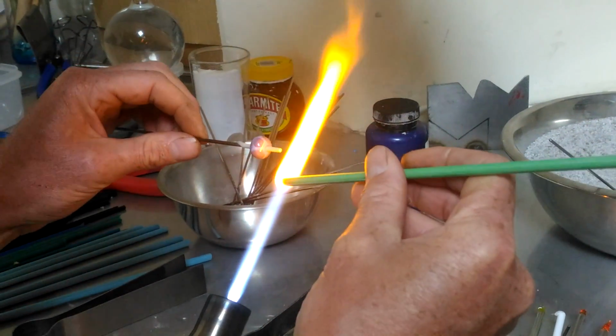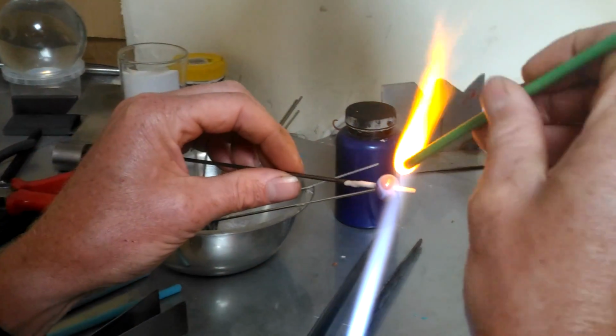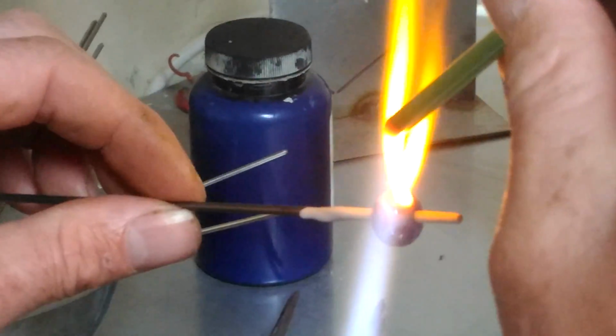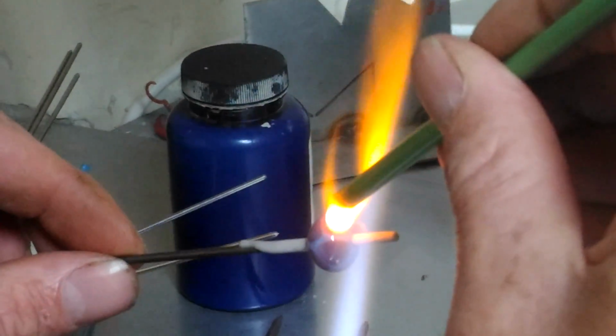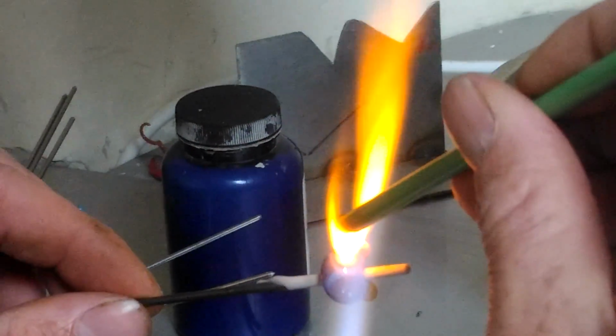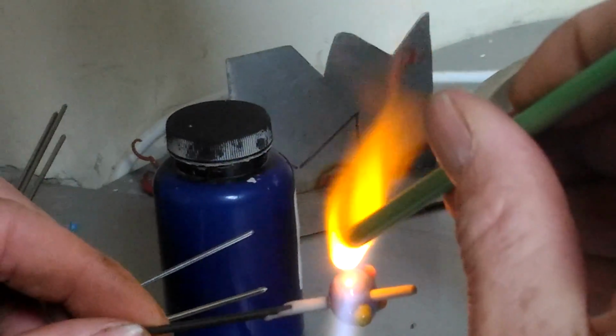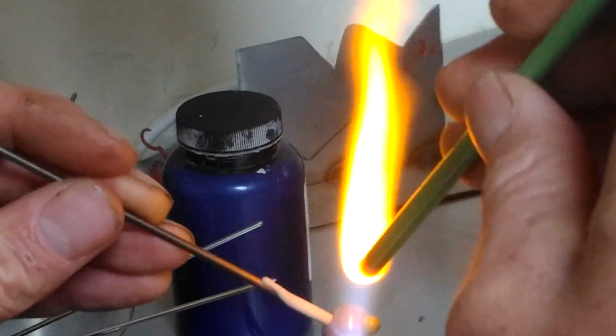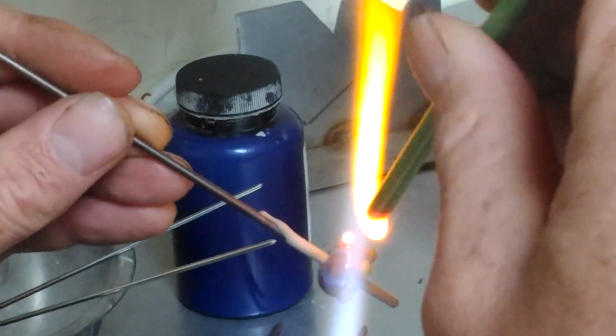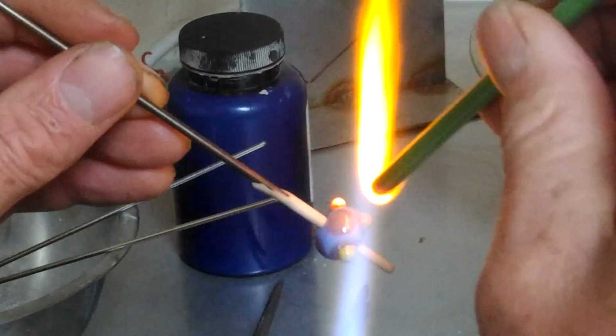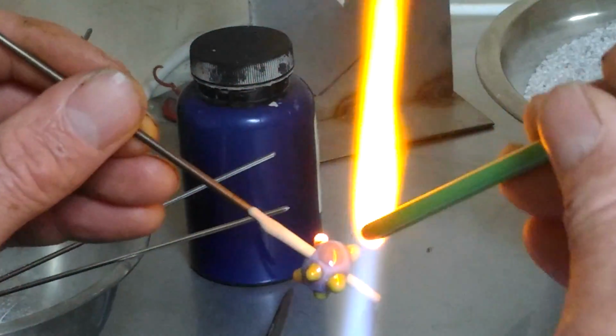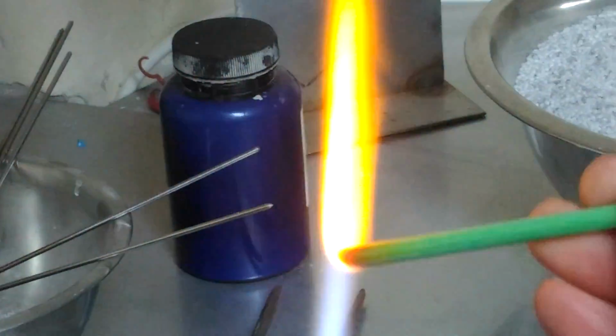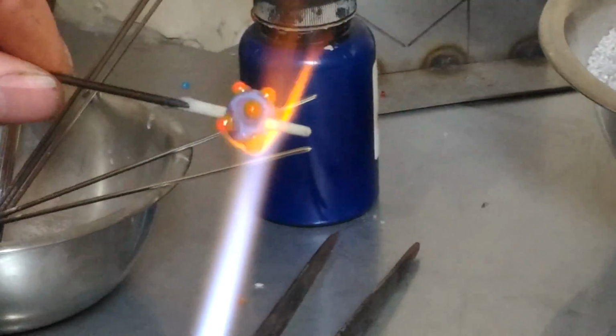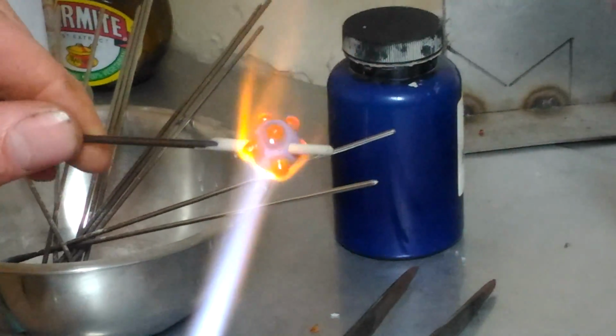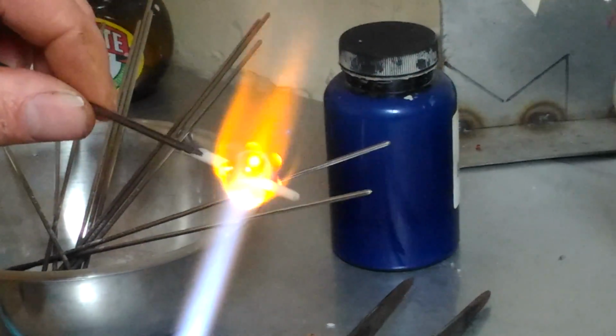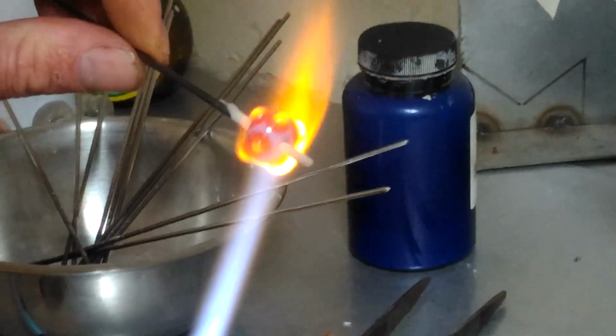Colors can also change a lot when they cool. The rod might look like one color, then when it gets hot it looks like another color, and then when the bead is finally cold at the end of the whole process, it'll look like a third color. So you have to get used to your glass. It's kind of alchemy in a lot of ways, the way the chemistry of the flame changes the oxides in the glass, because the color in all glass comes from oxides of various metals. The nicest translucent reds come from gold oxide, for example. Blues come from copper oxide and cobalt oxide.